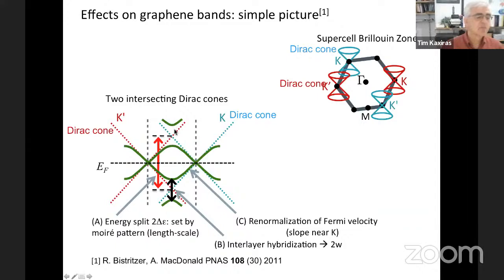And at the intersection points, you get a splitting of the energy levels. And this is what produces these green bands, the bands that correspond to the bilayer. And this is, of course, the very beautiful qualitative picture that was proposed first and described in some detail by the seminal paper, the landmark paper by Bistritzer and MacDonald.